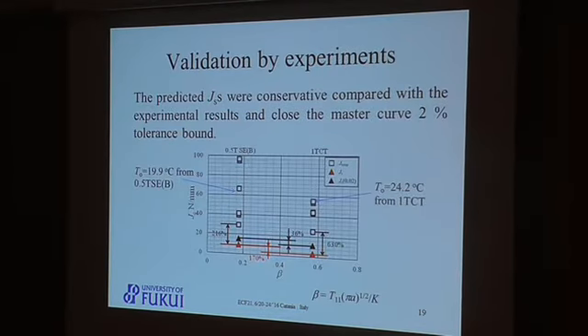Fracture toughness tests were conducted in accordance with ASTM E1921. The master curve reference temperature T0 for the 1TCT specimen was obtained as 24.2 centigrade. The test results were compared with the predicted JSs together with the master curve 2% tolerance bound values for half T and 1T specimens. We see from this figure that the predicted JSs were sufficiently conservative compared with the experimental results and close to the 2% tolerance bound values.